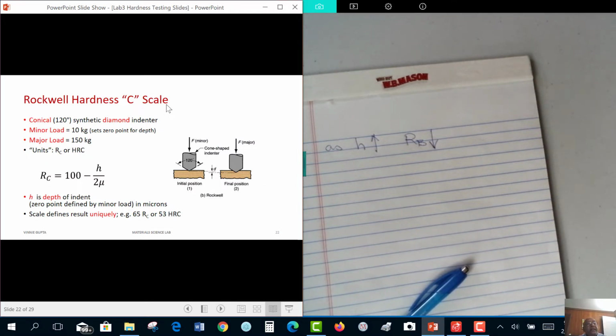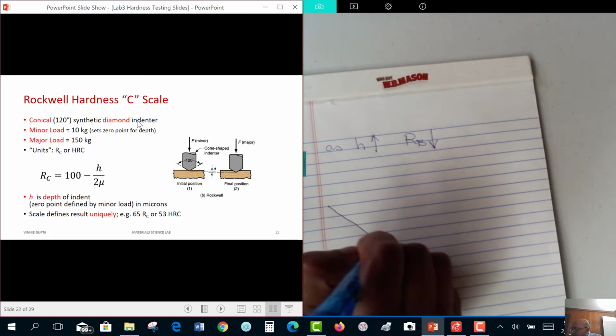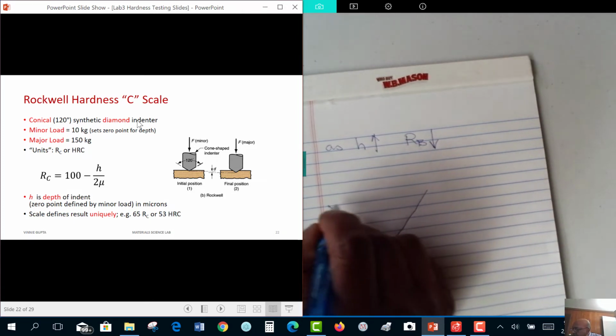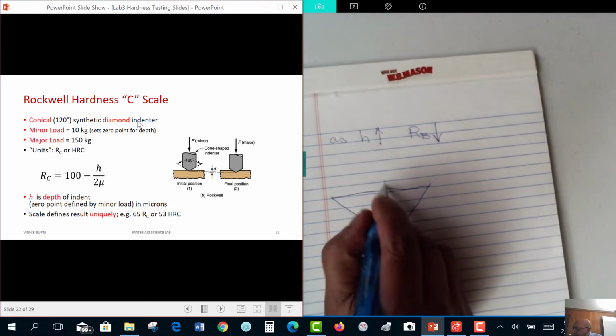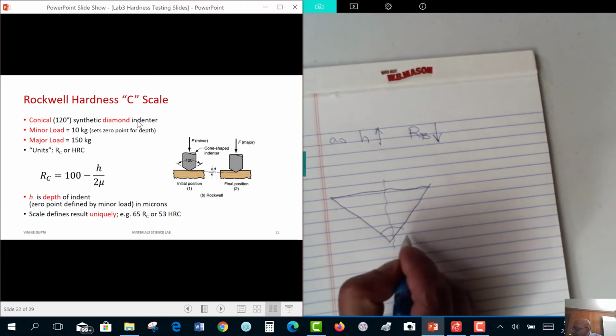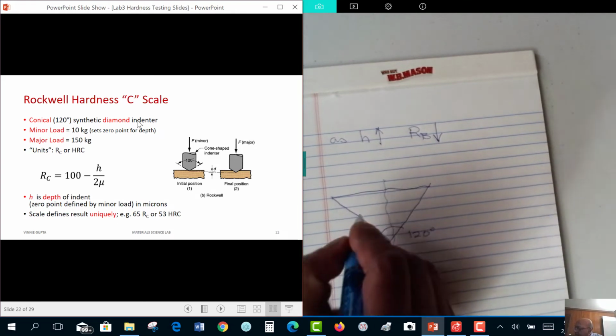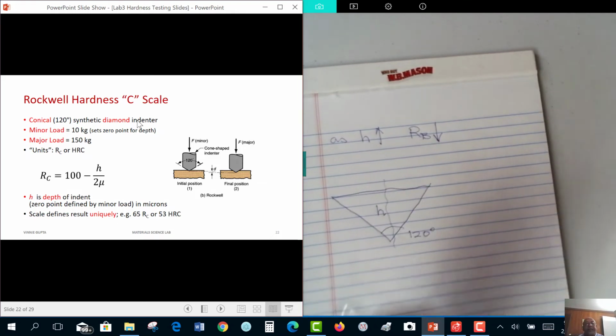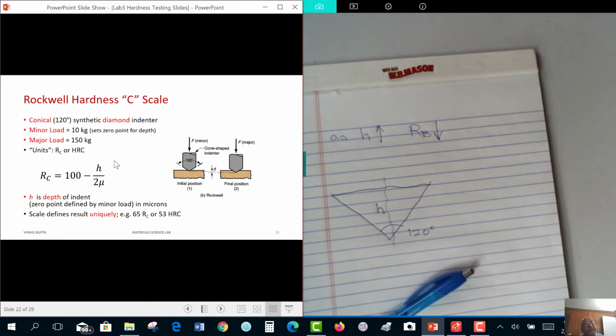In Rockwell hardness C scale, what we do is we use this conical 120 degrees synthetic diamond indenter. So our indenter is shaped like this, and this angle is 120 degrees. And this is our depth of indentation. Again, h is in microns. Same minor load, 10 kg. But this time the major load is 150 kg.